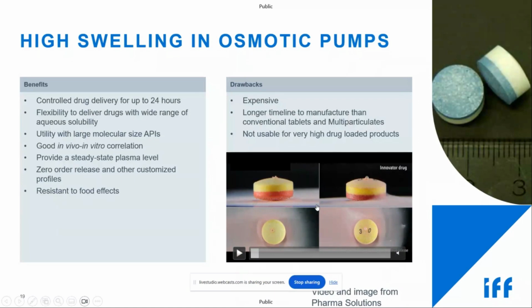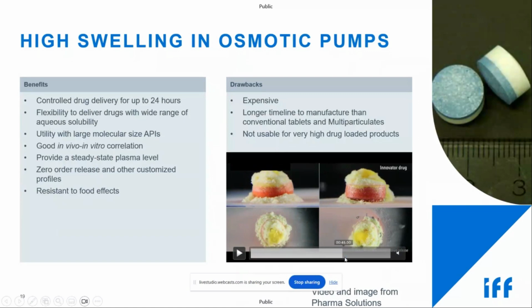What the semi-permeable membrane does is allow water in, but no drug out. What POLYOX is doing in the push layer is swelling and pushing on that drug layer to start pushing it out. There we go. You can start seeing the yellow coming out, pushing the drug out of the drilled orifice. As you see over time, this red layer is expanding as it absorbs more water and pushes out that drug until you get pretty much complete drug release, and this whole core is red from the push layer that contains a high molecular weight polyethylene oxide.